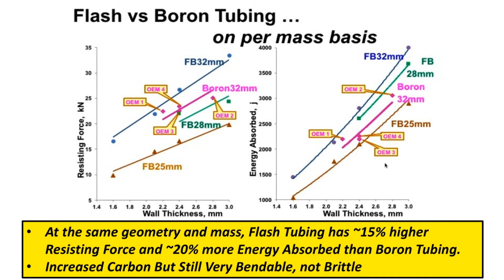What I mean by that is when flash bainite tubes are impacted and bend, the circle turns into an oval for quite some distance. Even at a 3-foot tube bent for 8 inches of deflection or 200 millimeters of deflection is still an oval. Now, if you compare a boron tube, usually after about 80 millimeters or 3.5 inches of deflection, it's already collapsed like a drinking straw and really isn't even working anymore. So yes, flash bainite does have a little bit more carbon for this test result here, but my goodness, if flash can hold its carbon and weld nicely, what does carbon really matter?